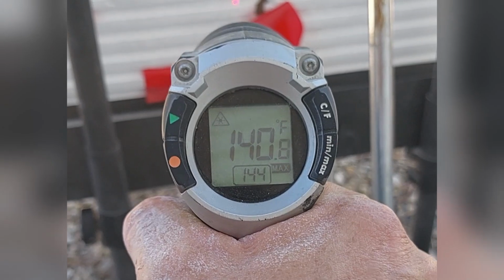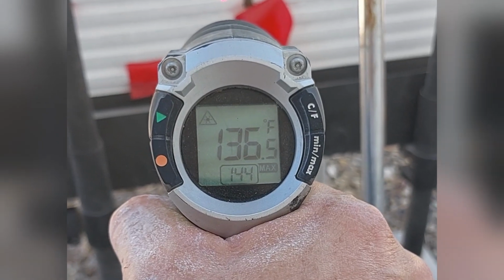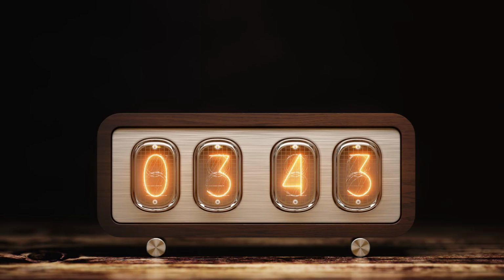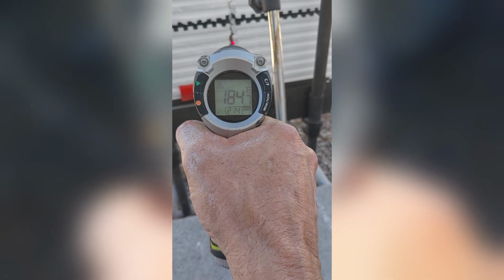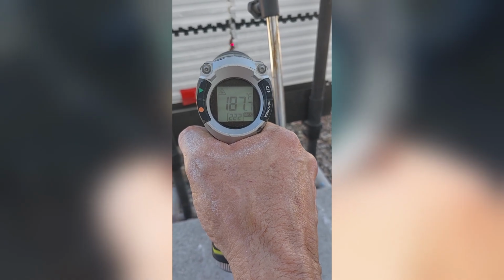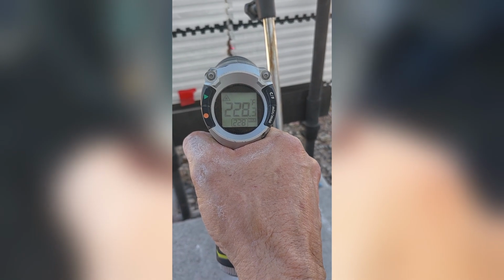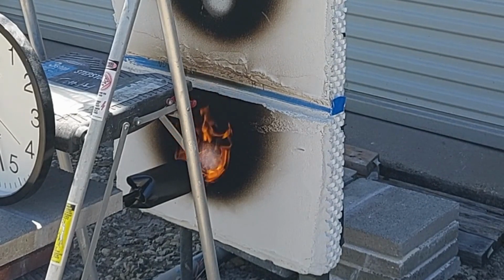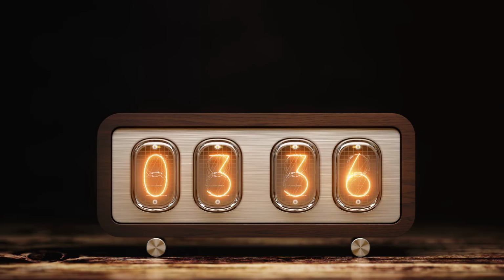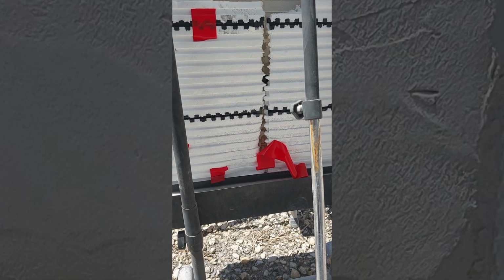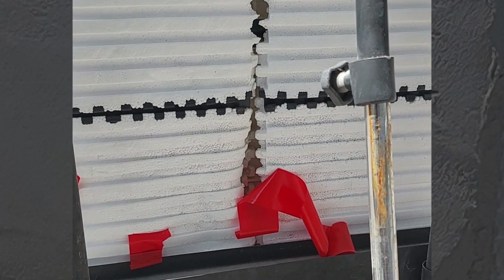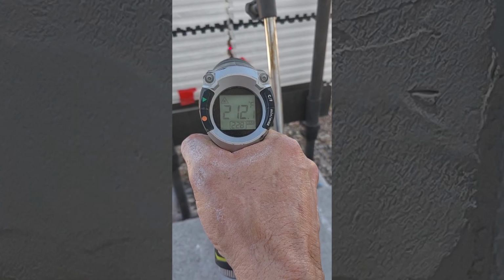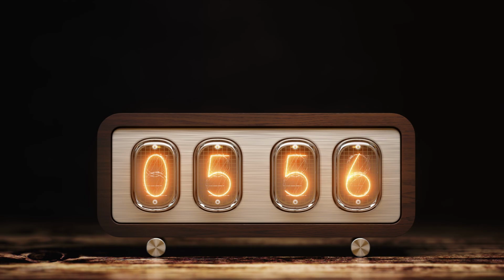The temperature reads around 130 to 140 degrees. At hour 3, temperature readings on the back side of the styrofoam panel have risen only slightly and are around 200 degrees. In the meantime, the flame in the front continues to burn at over 2000 degrees Fahrenheit. We're taking our final reading at the 4-hour mark. On the back, there is no degradation of the ICF wall styrofoam and temperatures remain stable. Seeing the extraordinary results that BioLime provided, we decided to continue testing and complete a full 8-hour burn test.